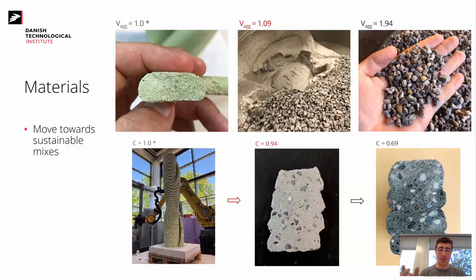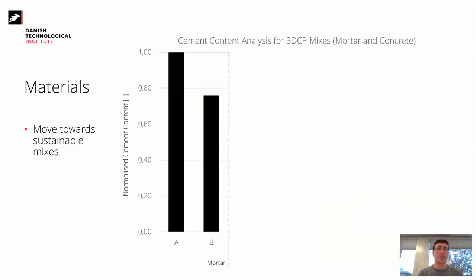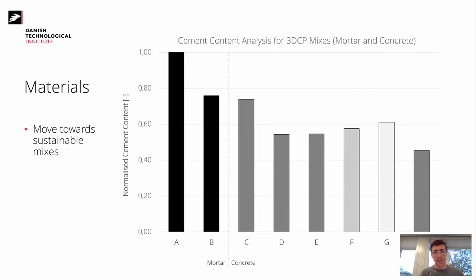In my case, it is concrete. It's a material that's sustainable. I mean, using large aggregates, and we've been successful in running some prints with that. So just to showcase how the cement content has been decreasing over the mixes that we have developed and tested here at DTI. These mixes A and B are within the mortar domain, where we had very high cement content. Mix A uses a white cement. Mix B uses a calcined clay-based cement, and then you'll see later how that impacts the CO2 figures of all these mixes. But when you go into concrete, that's mixes C and onwards, all of them have a reduced amount of cement content. Of course, we are adding large aggregates so that they're all extrudable, and again, I'll not go into details of these mix designs, but the shades of gray you see there are mix designs made with either different cement types or aggregate types.